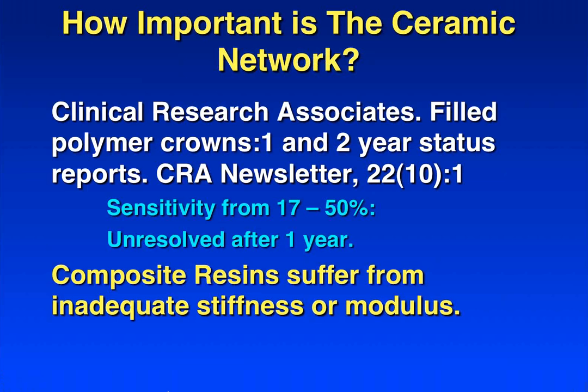Composite resins do not have a network. They have a filler. Years ago, fiber-reinforced network materials were very popular. There was Bell Glass, Art Glass, which was supposed to be the future of restorative dentistry. Didn't work out so well, ended up in a lawsuit. Targis Vectris and MZ100 were all studied by CRA, and they made composite resin crowns out of them. One of the big problems they had with all of the materials was sensitivity. And composite resins just don't have an adequate stiffness to resist stress when you get to very large restorations.